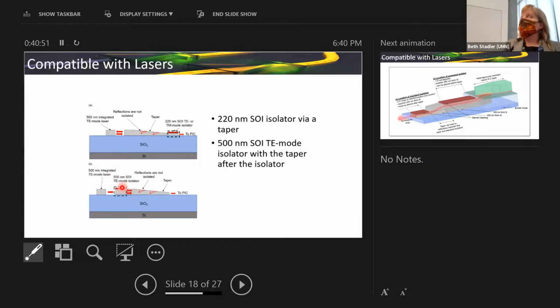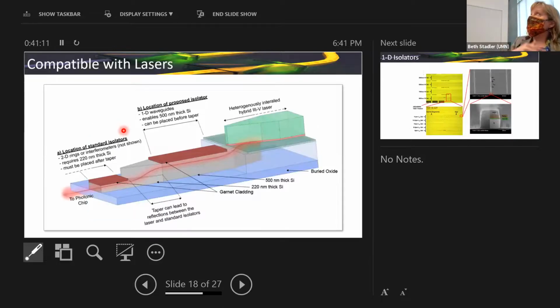All right, so I guess what I like about the non-reciprocal mode conversion is we even have garnets that are good enough, these terbium iron garnets, that we could do this on a 500 nanometer core. And that means that a lot of lasers couple in one way or another to a thicker core, and then you taper, and you can get reflections in the taper. So if you need your isolator to be 220 nanometer, you might have a lot of reflections already by that point. And so this was the schematic that Kartik made up to show maybe this is another way you're going to take your laser light coupled into a thicker core. But if your garnet could be here, then you're not worried about this taper reflecting a lot of light back.